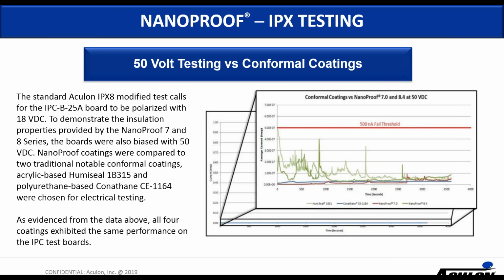So we figured we'd step it up a little bit and run a test at 50 volts. This is both 7, the 8 series material, and then we also threw two conformal coatings, an acrylic-based and a polyurethane-based conformal coating into the mix. And as you can see, both the 7 and 8.4 fell well below the 500 nanoamp threshold at 50 volts.